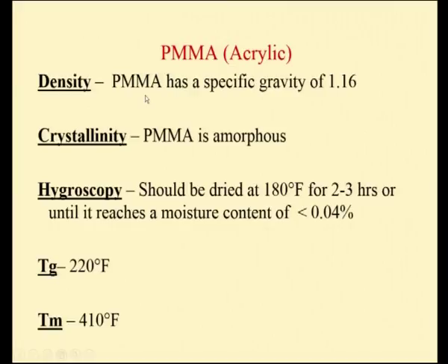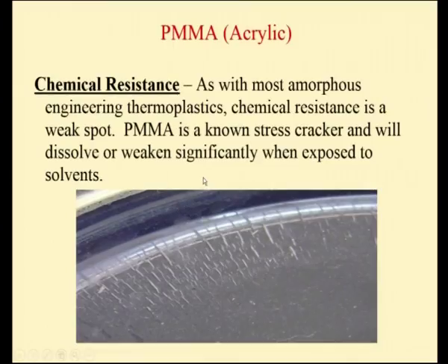In the case of density, PMMA has a specific gravity of 1.16 and the crystallinity is amorphous. There is no crystalline structure available. In the case of hygroscopy, it should be dried at 180 Fahrenheit for 2 to 3 hours or until it reaches a moisture content of 0.04%. The glass transition temperature is 220 degrees Fahrenheit, whereas the melting temperature is 410 degrees Fahrenheit.